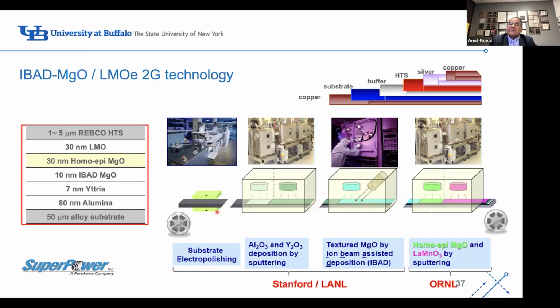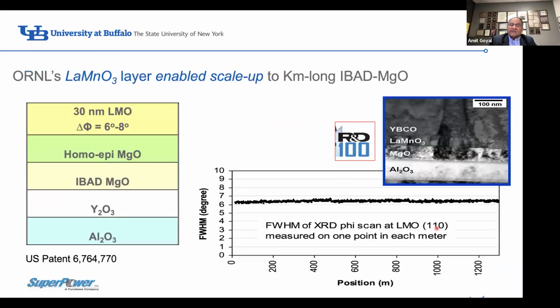Here, in this case, the metal substrate has no atomic orientation. And then we deposit the lanthanum manganate layer here, which is a key layer which allows transference of the texture from this layer to the superconductor without detrimental reactions. Here is an example of a 1.2 kilometer long LMO MgO wire. You're looking at the in-plane orientation of the lanthanum manganate layer.